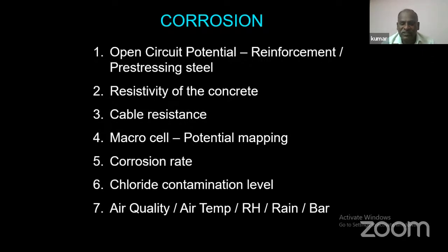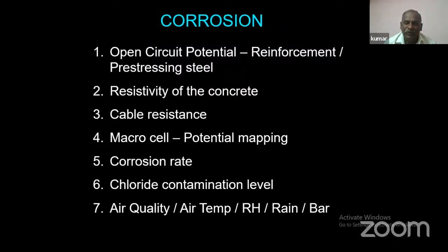Next one, cable resistance. In pre-stressed concrete bridges, you have the cables for post-tensioning and pre-tensioning. Those cable resistances can also explain the status of the steel cable within the concrete. Then macro cell, we have to make a potential mapping. When you make the potential mapping, we can identify the location where the corrosion initiates. Those vulnerable locations you can identify, and you can attempt rehabilitation, then you can solve the corrosion process in your structure.